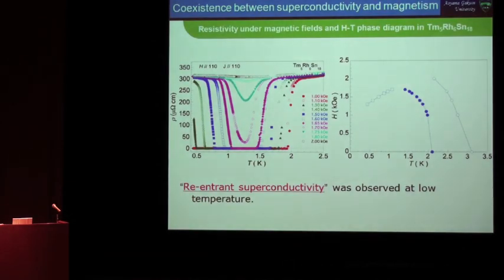One of the interesting points is that under zero field, it shows a very beautiful resistivity drop to zero. However, under a very small magnetic field, reentrant behavior appears. So the superconductivity at zero field is just like this, but under very small magnetic field, reentrant behavior appears. So reentrant superconductivity was observed at low temperature, and this is a phase diagram.